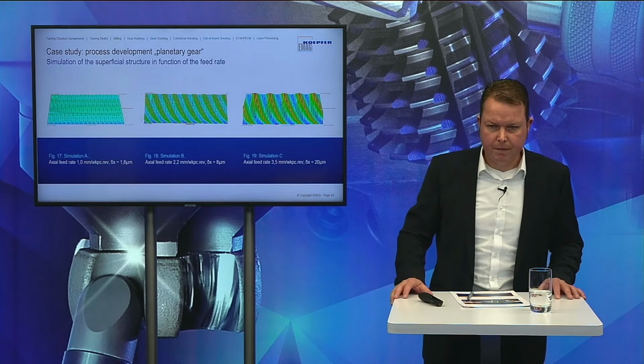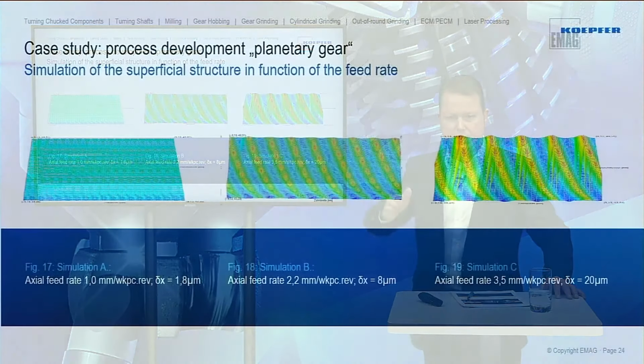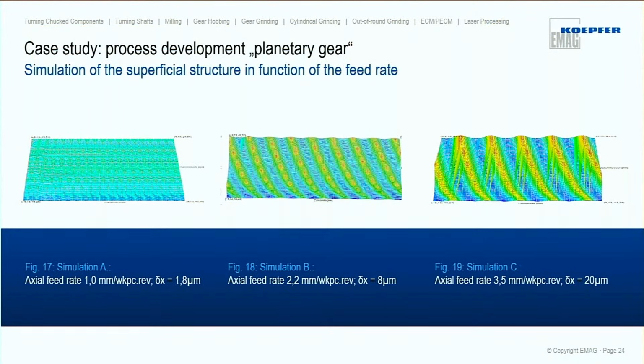And we have done exactly the same by means of a variation of the feed rate. You can see in picture number 1 an axial feed rate of 1 millimeter per workpiece revolution, leading to a depth of the feed scallops of 1.8 microns. Then simulation B, 2.2 millimeters per workpiece revolution, 8 microns, and 3.5, 20 microns. And I think it's quite obvious to see that this has a huge impact on the topography. And you can also see by means of the figures that there is an influence that is non-linear. That means if I increase the feed rate 2 times, I will have 4 times deeper feed scallop marks.